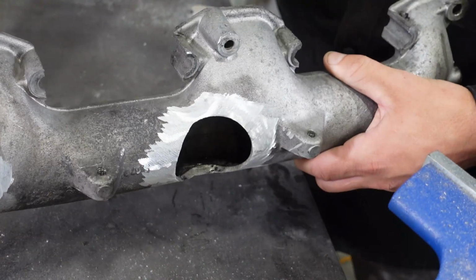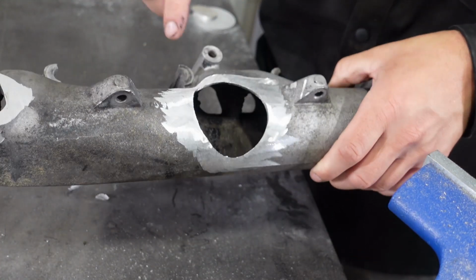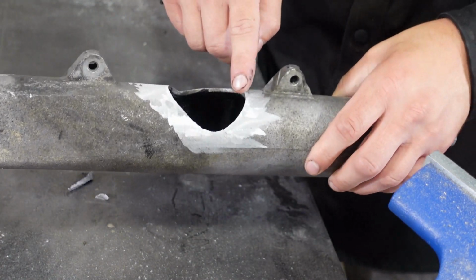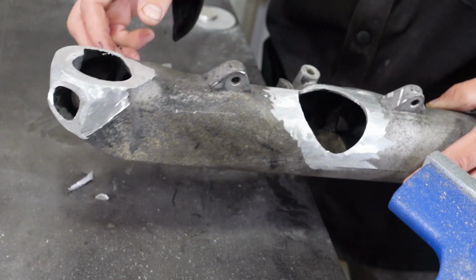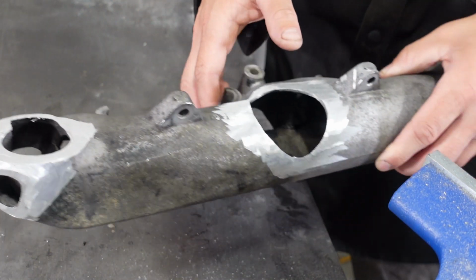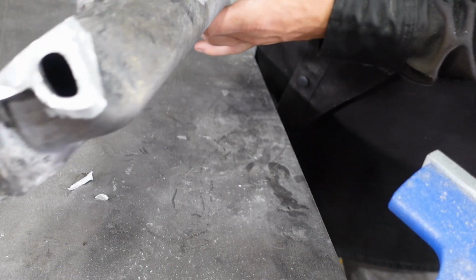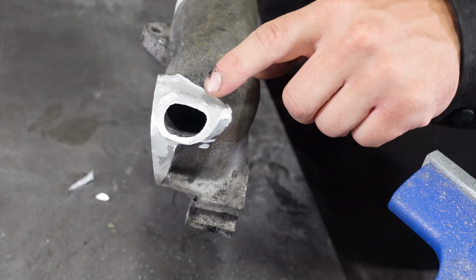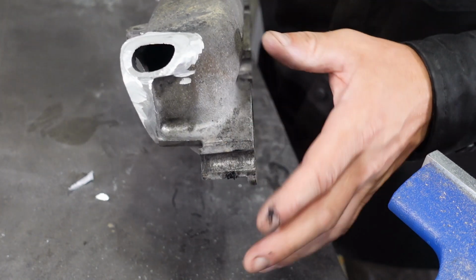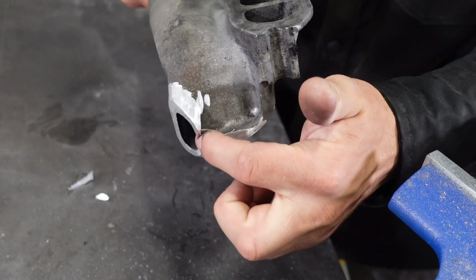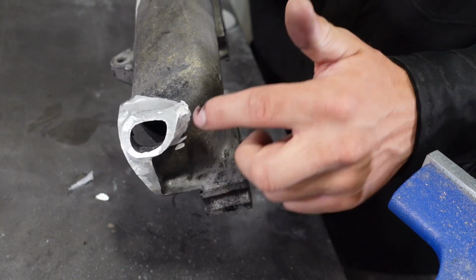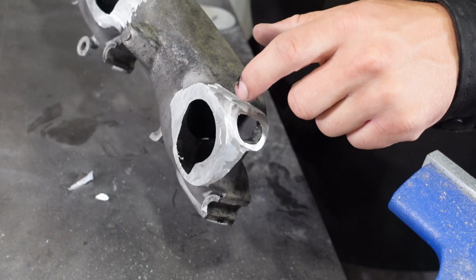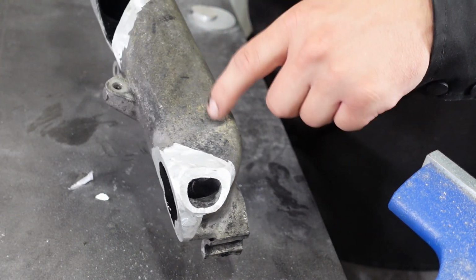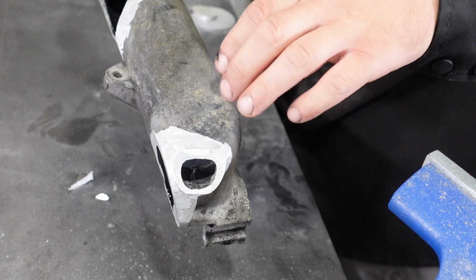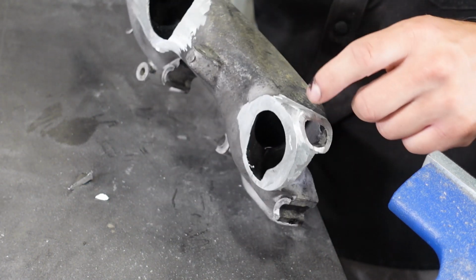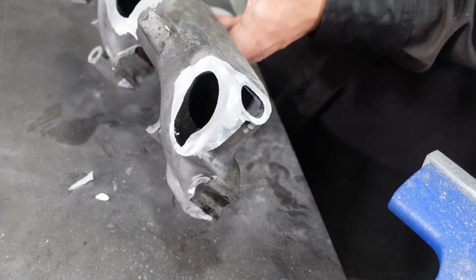So here is our prepped product. Now, it's safest just to go ahead and go beyond your welding surface. Even if you don't think you're going to be welding on something, but you think there's a chance that you could butt up to it, especially on your EGR, I like to just clean everything I can up on here, because a lot of times you'll end up overlapping out onto this area. And as soon as you get into this dirty cast material, this top surface here, it'll suck it into your weld. You'll get porosity and then you'll have to grind your whole weld off.